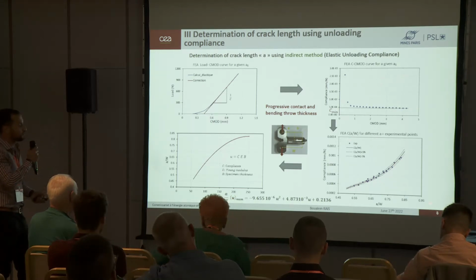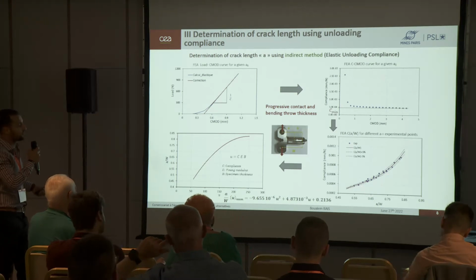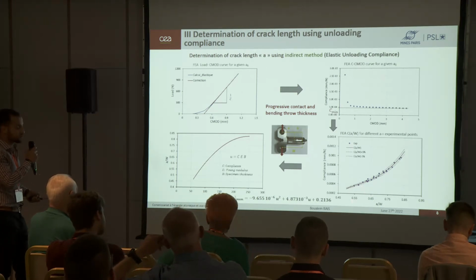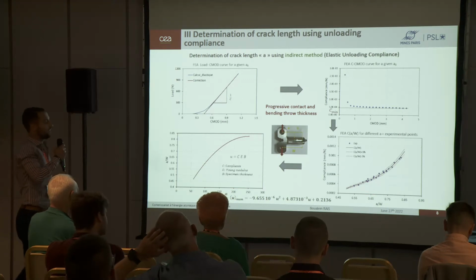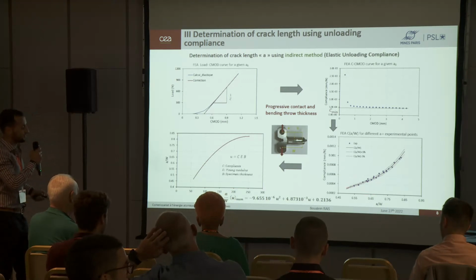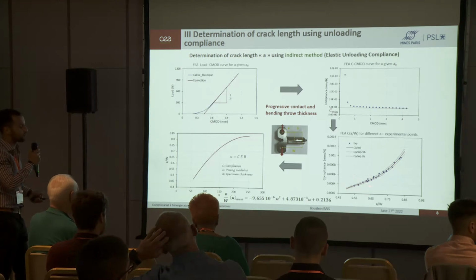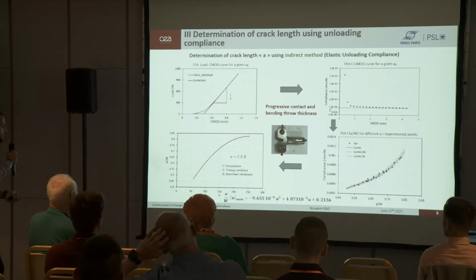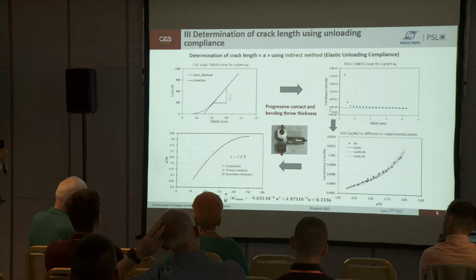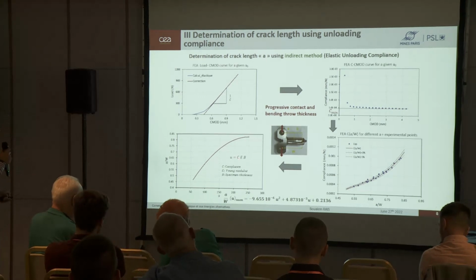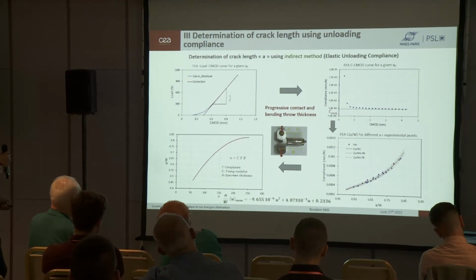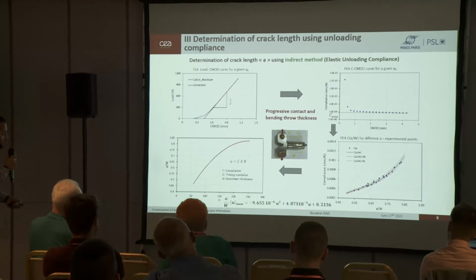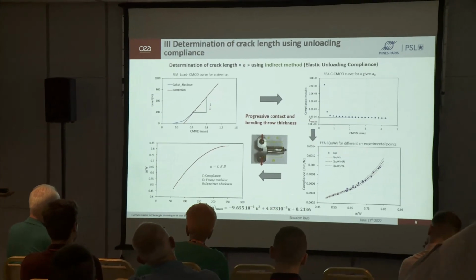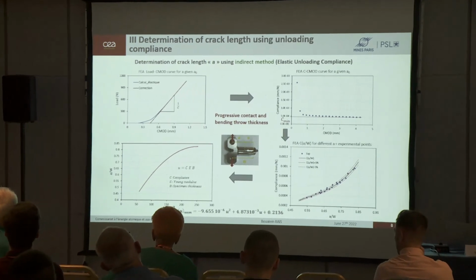So we do this for different crack lengths to have the evolution of the compliance as a function of the normalized crack length. And as we can see, the numerically defined C function is in accordance with the experimental results, the blue points. After that, we introduce this factor U, which is just a normalization of the compliance by the Young modulus of the material and the specimen thickness, and establish this equation permitting us to determine the crack length.